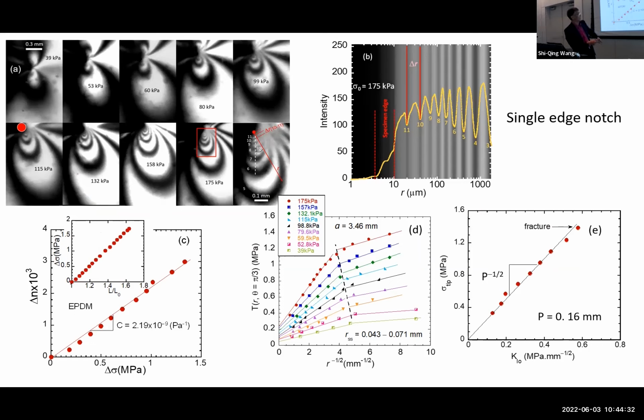It's boring, right? So it's just like plastics. The stress stops building. In other words, you show a big kink around a scale that's manageable, 50 microns to 100 microns range. And again, the tip stress keeps building. You see, without this plateau, the last point is at infinity because it's inverse. Without this plateau, I wouldn't be able to confidently tell you what the tip stress is. So this is the key. If this thing keeps going, then go ahead and resolve it because it will go forever. That's the window glass. You can never do this experiment. Can never resolve below wavelengths of light. So with this, we find again it's linear. That slope, 160 microns.